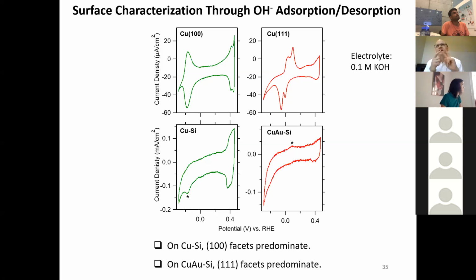So there's two parts to answer this question. The first is we have different types of cations and anions that may specifically adsorb, which, for example, the sodium perchlorate would not. So that would be consistent with a more negative potential of zero charge. We just need to go more negative to, for example, repel any specifically adsorbed anions, like our borate or chloride, depending on what anion we have been using.